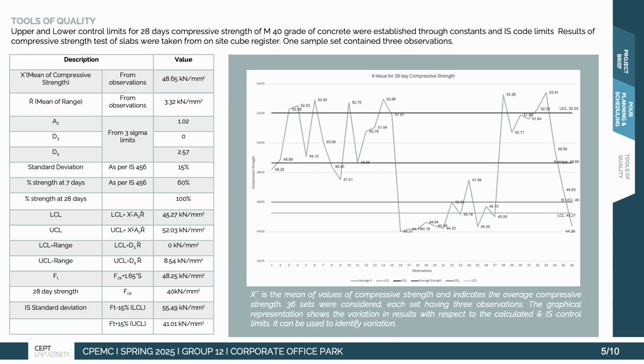Next is the tool of quality. We established control limits for compressive strength test of concrete of M40, which is used in slabs. The result of compressive strength tests were taken from the on-site cube register, and one sample set contained 3 observations of compressive strength of cubes. The table shows the X bar, which is the mean of compressive strength, and the value was 48.65 kilonewton per meter square. R bar was the mean of range, which was 3.32 kilonewton per meter square, and R bar is the difference in compressive strength of observations within one set.